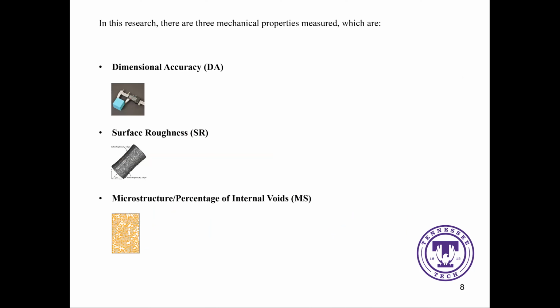In this research, since this is a very new technique, we just measure 3 properties, which are dimensional accuracy, surface roughness, and the microstructure or percentage of internal voids. The dimensional accuracy is the shrink ratio of the final parts compared with the design parts. For the surface roughness, we use Ra numbers because it's the most widely used one, and we measured it with an SJ-210 surface roughness tester. For the microstructure, we compare the theoretical mass and the real mass. The difference between them is the percentage of the internal void, because the void does not have any mass.